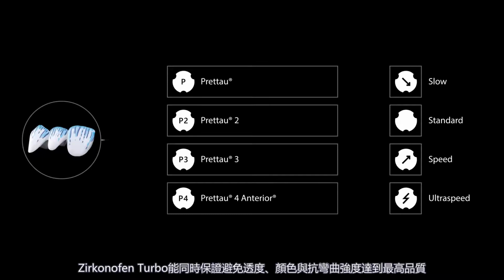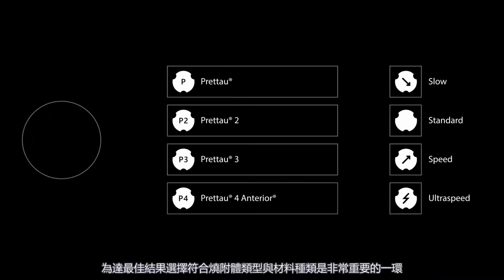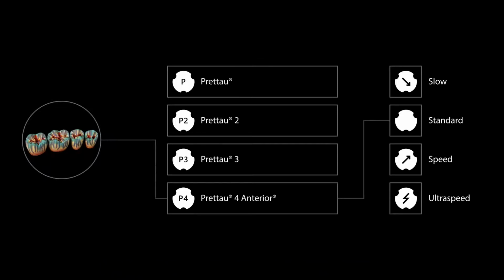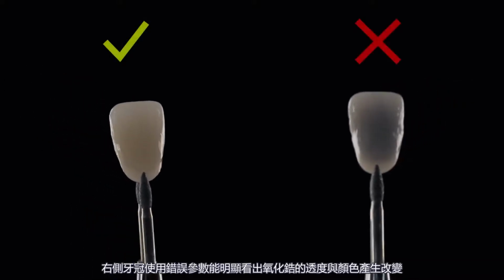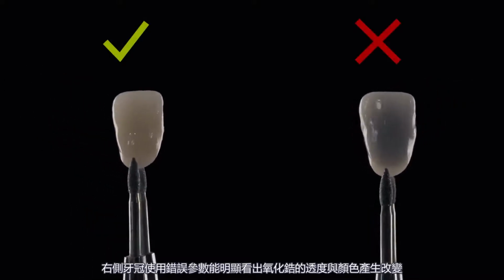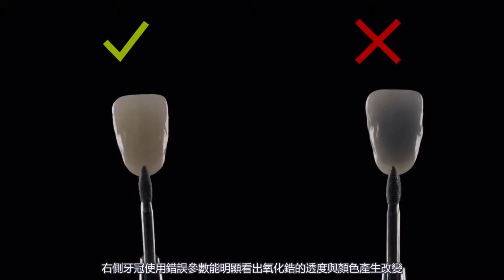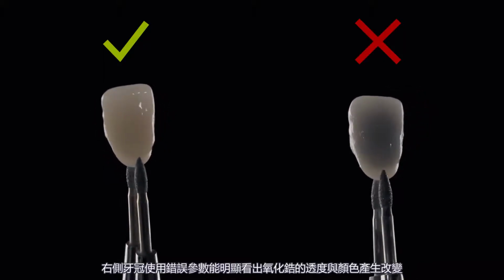To ensure high-quality results and avoid discrepancies in translucency, color gradient, or flexural strength, it is necessary to select the sintering program that corresponds both to the material and structure type. The crown on the left was properly sintered, whereas the one on the right was processed with incorrect parameters, which altered the translucency and color gradient of the zirconia.